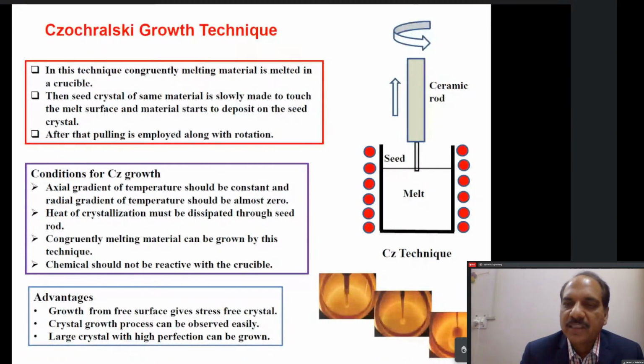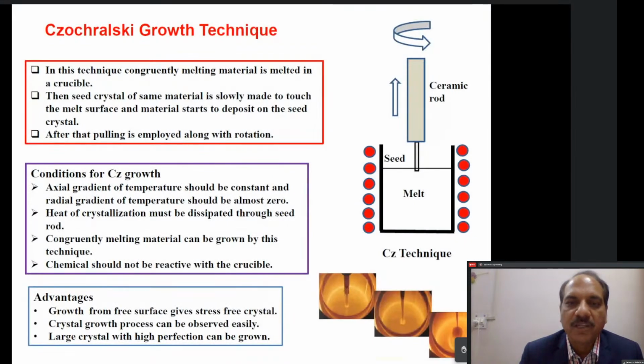And after the platinum crucible is loaded with the charge in the furnace, we heat up the furnace, following a particular temperature program so that it reaches up to the melting point. And we melt. In case of lithium niobate, it is 1250. So we heat it up to 1250 degrees. The furnace is slowly ramped up, and the charge is melted.